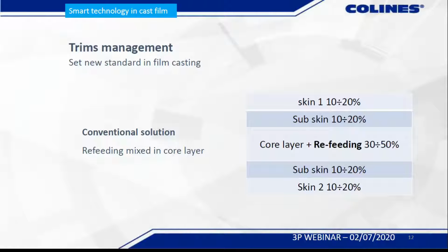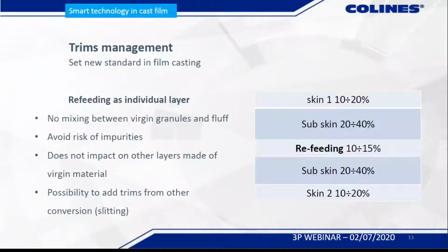But the new solution we have already supplied to 2 machines is refeeding the fluff as an individual layer, always in the middle, but there is no longer mixing between virgin granules and fluff. You avoid at all any risk of any kind of impurity. If you match it with the new screw, the film becomes like glass. It does not interact with other layers made of virgin materials, and clearly this percentage shows 10 to 15% when it is about the machine trims. But if you also want to include trims coming from other slitting operations, for example, this percentage might come up to 20%, but we didn't see any problems going to that percentage.